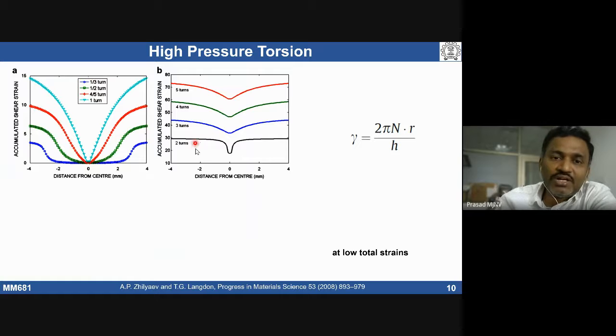Beyond 1 turn, if you go for 2 turns or 3 turns, the accumulated strain is going to be higher, no doubt about that. The shear strain is going to increase with the number of turns, and we do see a reduced change in the accumulated strain between the center and the surface. Nevertheless, we do see some gradient in the strain from center to surface of the disc under high pressure torsion conditions.